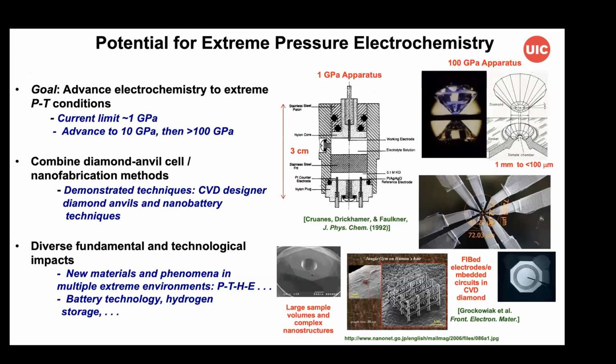So how would we do this experimentally? This is sort of a grand challenge for us, but the idea would be to take the high pressure electrochemical apparatus approach that Harry Drickamer developed in the 1960s, shown here in this plot in the middle, a 1 GPa apparatus where he was able to do high pressure electrochemistry, basically in the 10 kilobar range, but extended up into the 100 GPa range with diamond cells, and use basically various types of nanofabrication tools to build miniature electrochemical cells inside the diamond anvil cell. So this would be an interesting marriage of sort of battery technology and hydrogen storage material technology at high pressure. So a challenge for experiments.